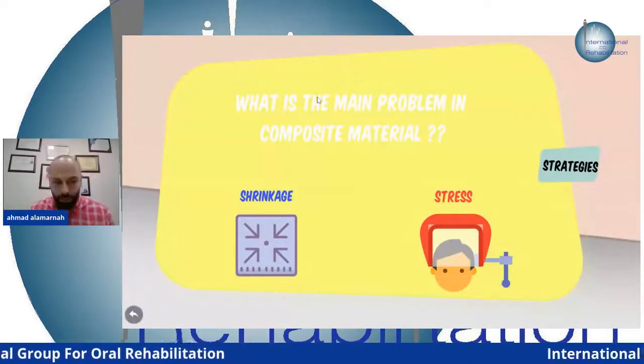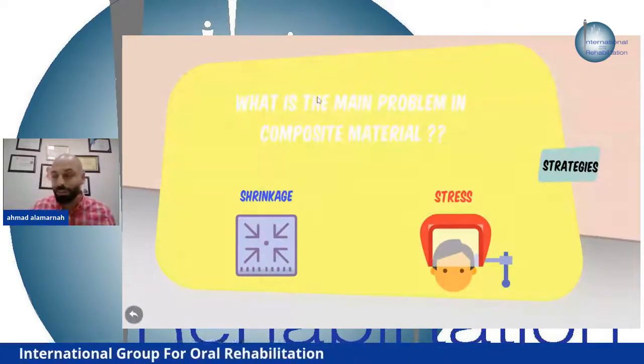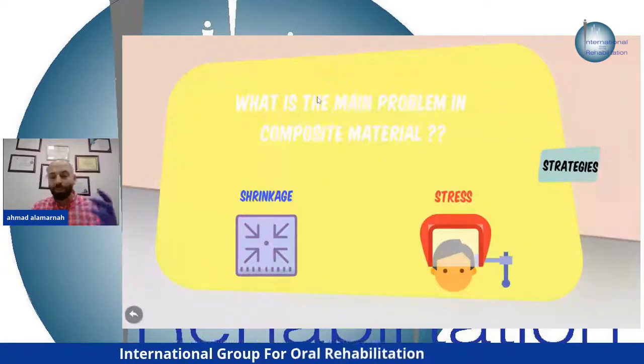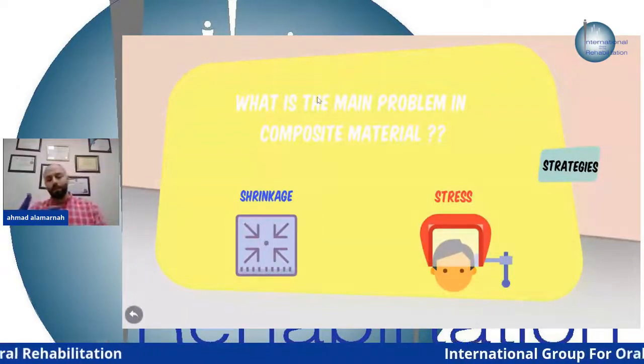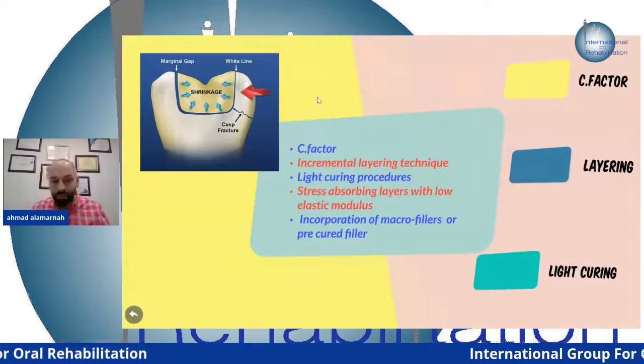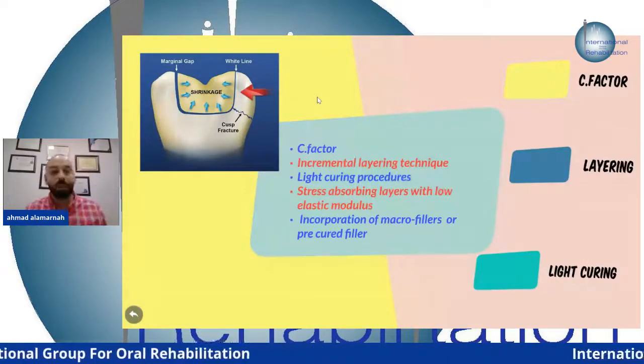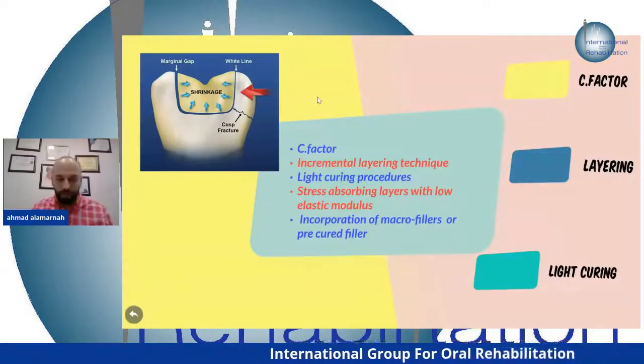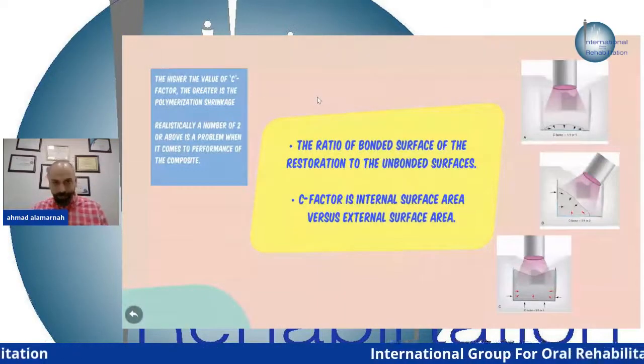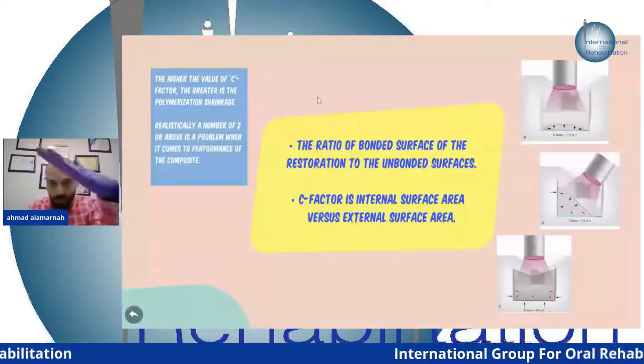The main problem of composite restoration is shrinkage, which causes stress. The composite shrinks toward the center. Strategies to manage this include C-factor management, incremental layering technique, light curing techniques, stress-absorbing layer using flowable composite, bulk-fill flowable composite, and incorporating macro-filler or pre-cured filler. The C-factor is the ratio of bonded surfaces to unbonded surfaces of the restoration.